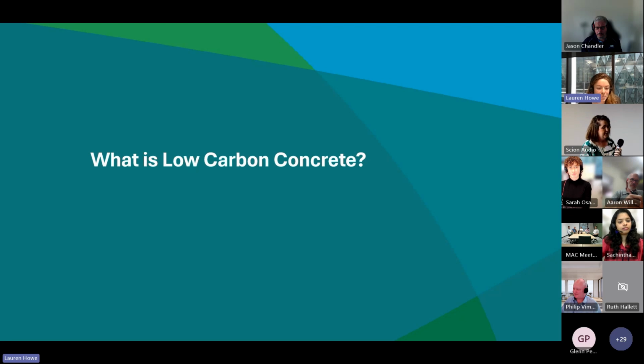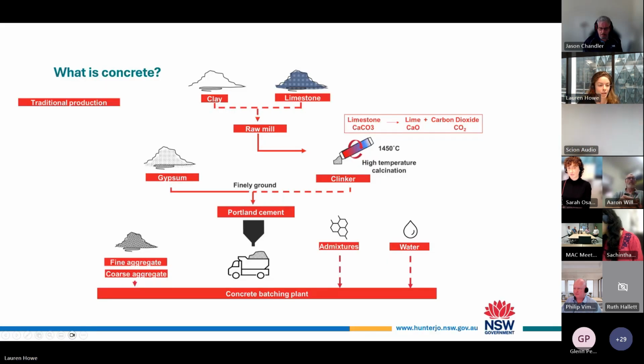What I'm about to talk us through, sorry to the councils that have already gone through the training sessions with us, you would have seen some of these slides before, but we just want to get everyone on the same page for moving forward in this workshop today of what actually is low carbon concrete. If we step back to the most fundamental level of what actually is concrete, concrete is a mixture of different constituent materials. This includes cement, aggregate, sand, different admixtures, and water. We make cement by heating clay and limestone at very high temperatures of up to 1450 degrees, and then we grind it together to make a clinker. This clinker is then mixed with a small percentage of gypsum to create your Portland cement. We add the gypsum to the clinker to slow down the reaction of that clinker with water, otherwise it would react too quickly.